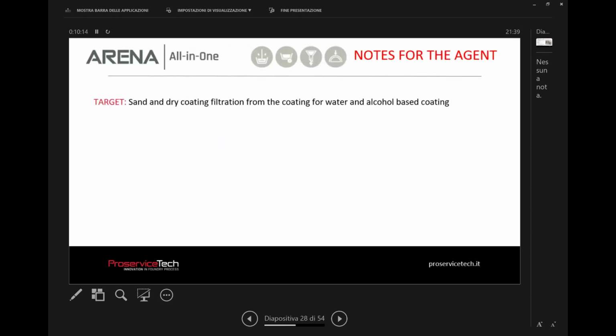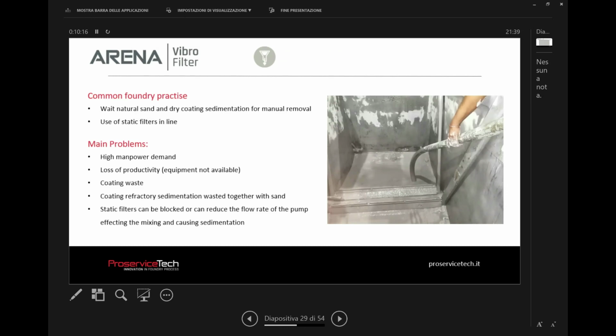This is another simple machine, a vibro filter for removing every single part of sand particles from the deep tank. You can use it as a dialysis, so you can clean. You can use only one of these machines, but connect it to many deep tanks, 1 hour per day for example, and it is able to remove every single particle of sand. So you don't need to clean the tank frequently. This is used, for example, in no-bake foundry to avoid sand particles on the surface of the core, but also for cleaning the deep tank. It works in this way.